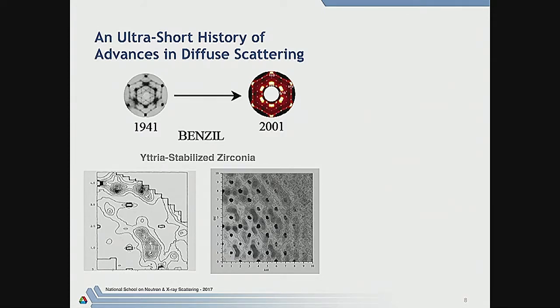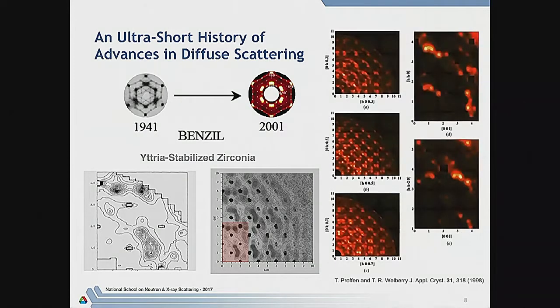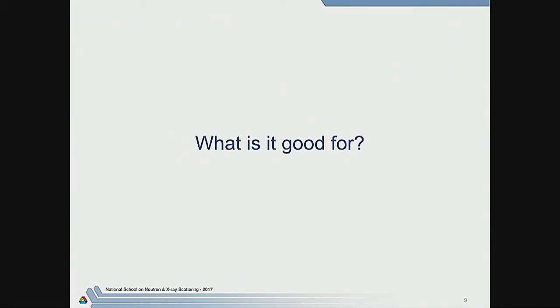This is SXD, which is at ISIS. It's very similar to, say, Topaz here. They looked at the same material about 2003, I think it was. And you can see here, this is the Q range we covered with the triple axis. So they covered a much bigger Q range, and it was all three-dimensional, and they did it in just a few hours. It's important that you get all three dimensions, because if you have a rod in two dimensions, you don't know whether it's really a rod or whether it's a plane in the third dimension. So you really want to have three-dimensional data. Okay, that's the history of diffuse scattering.